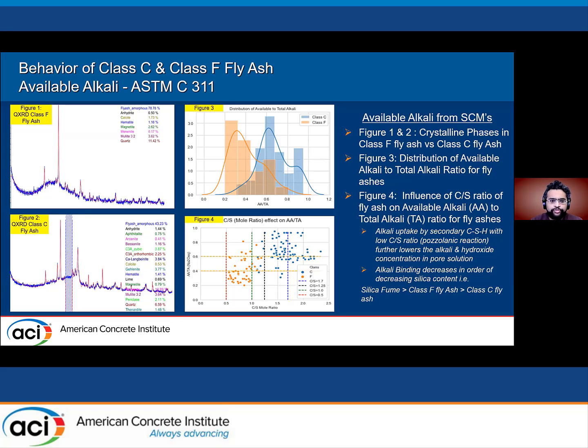If you look at Figure 4, the lower the C to S ratio, or the higher the silica content, the lower is the available alkali as a fraction of total alkali. And this phenomenon, also known as alkali binding, decreases in the order of silica fume, class F fly ash, and then class C fly ash.